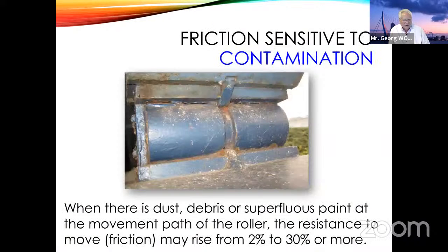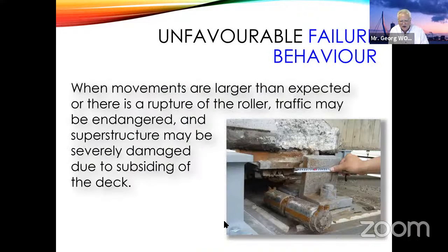Another problem we found is contamination. A lot of the roller bearings couldn't move anymore because a lot of debris and dust came to the roller level, and also we sometimes had people painting the bearings much too much. If you see here the paint, it happens that the friction went up a lot, and then the bearings were the reason that the bridge had to behave like an arch bridge and not like a flat bridge. Another problem with those bearings was that in some cases the movement was too much, the roller was rolling out, and then of course it has a very bad behavior, the bridge is going down.